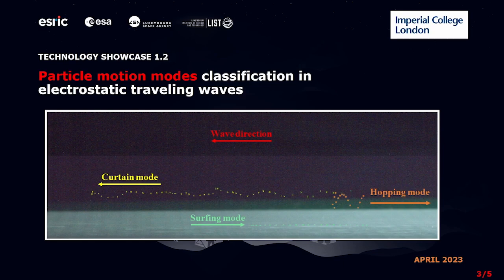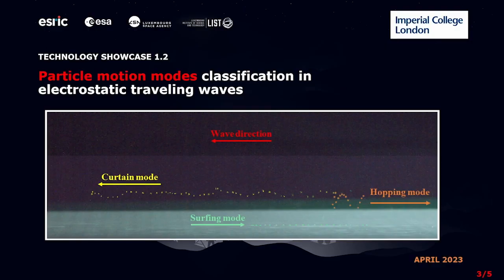As particle size becomes larger, it can only navigate close to the surface where the electric field is strong. As it navigates away from the surface, the intensity of the electric field drops quickly. Therefore, it will drop down. This alternating falling and bouncing movement is called hopping mode. When particle size becomes even larger, it may only move along the surface without navigating at a certain height. It's like people surfing along the sea wave, so it's called surfing mode.